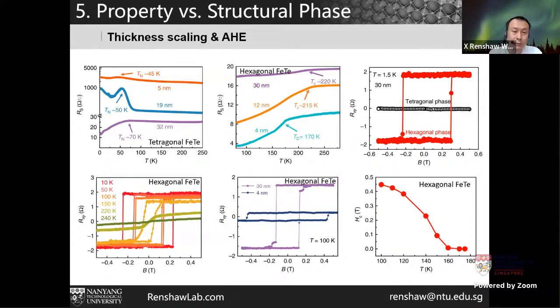For example, here on the bottom left side, the hexagonal phase, we can vary the temperature. We can see how the anomalous Hall effect evolves as we ramp up the temperature. Of course, by measuring the anomalous Hall effect as a function of the temperature, we can further confirm the TC. So that's why we are able to confirm that the TC is around 200 K.